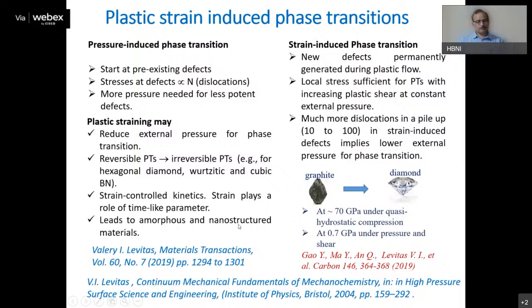So in case of pressure-induced phase transition, the phase transition should start at pre-existing defects. So it very much depends on the defect concentration of your sample. This is not very important in case of oxide samples or very brittle samples. But in case of metallic systems, this becomes very important. And that is the reason why many researchers report different transition pressures for the same system. For example, in zirconium, in static high pressure experiments, there is a range of transition pressure from alpha to omega, from 2 GPa to 7 GPa.